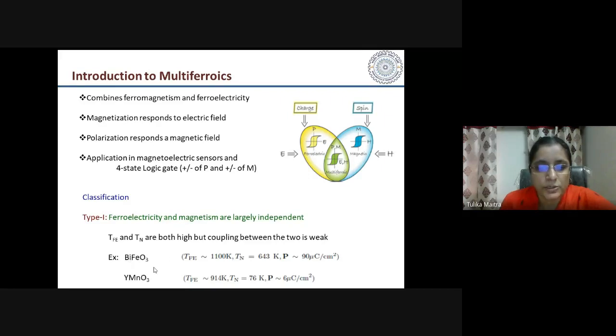These are some examples of these type 1 multiferroic compounds, where you can see that generally the ferroelectric transition temperature and the magnetic transition temperature are both high, but the coupling between the two is weak. So when we apply a magnetic field to tune the polarization or an electric field to tune the magnetization, the sensitivity becomes low because of this weak coupling. Though the transition temperatures are very high, so for application purposes these are very useful. These are two of the famous compounds that have been studied a lot.